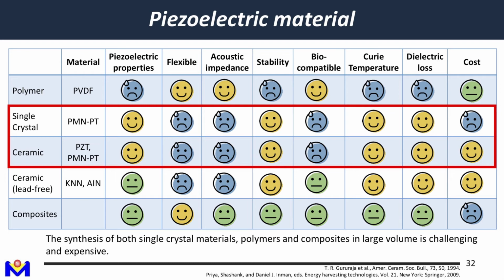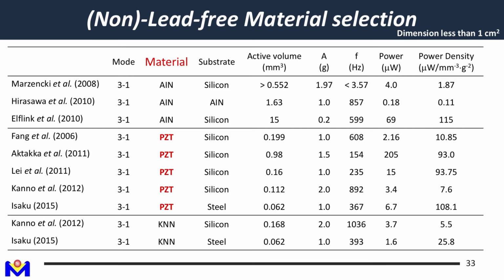So there are some different comparisons, like flexibility. Polymer is definitely better, but for the dielectric constant and the piezoelectric property, the single crystal or ceramic one is definitely much better than the polymer one. So for now, we still feel the ceramic one, PZT or PMN-PT, is the best choice for small scale energy harvesters at this moment. And for CMOS compatible processes, people like aluminum nitride or aluminum oxide. But these two general microfabrication or semiconductor process compatible materials have much worse piezoelectric property compared with PZT. So this is why for the past 10 years there has been a lot of effort on growing thin film or thick film PZT for different small scale piezoelectric transducers.